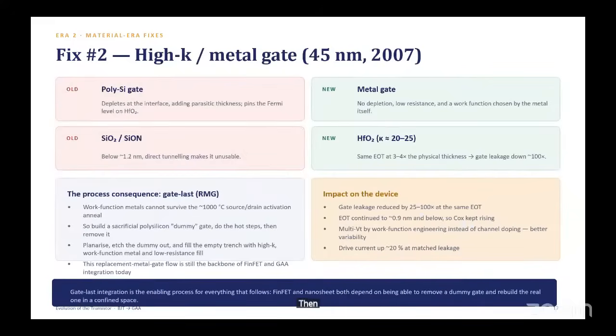Then the industry tried to work around the gate. We had a poly gate which controlled the electrostatics, and an even older version where the oxide was silicon dioxide or silicon oxynitride. So again, we introduce a metal gate. When you introduce a metal gate, the work function changes, but the second-order effects due to those tunnelings are better controlled. And you have a much better oxide coming in, a better dielectric with a K of 20 to 25. That brings down the leakage also. So without any change to the structure, purely by changing the recipe, the industry is able to get some improvements.